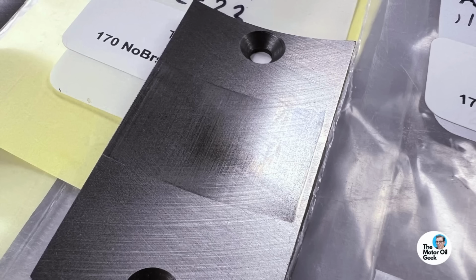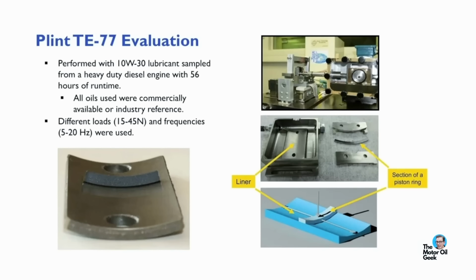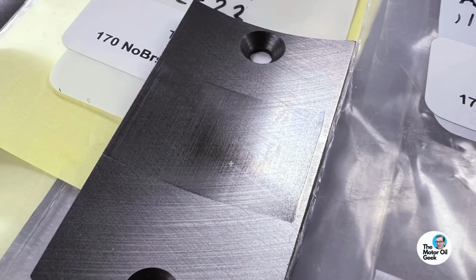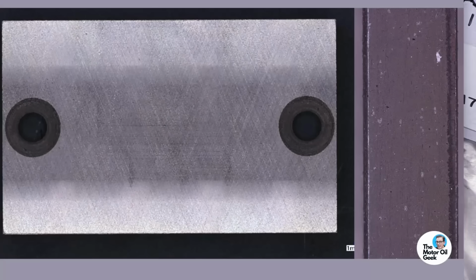Then I had to go back and take a look at the results of the coating testing we did at Southwest Research and compare it to oils just like this. Then I saw the difference. When we look back at the test specimens from the ring on liner testing we did with Southwest Research, that's where the light bulb turned on for me. What you can see right here is the wear scar with the regular coating and the regular honing method. There's a pretty big difference when you compare that to this. There was so much less wear with the variable hardness coating when we did the ring on liner test.